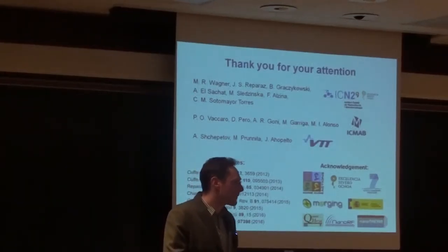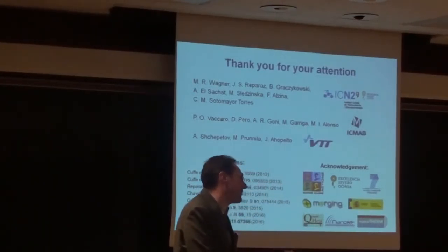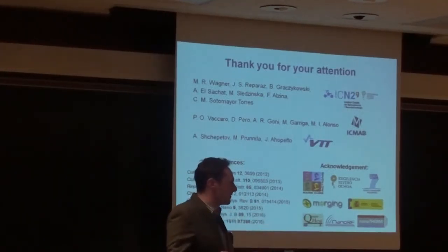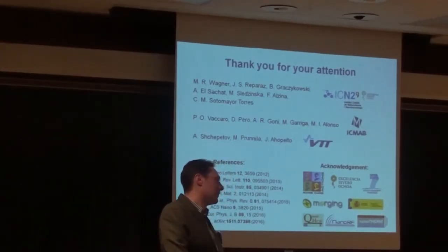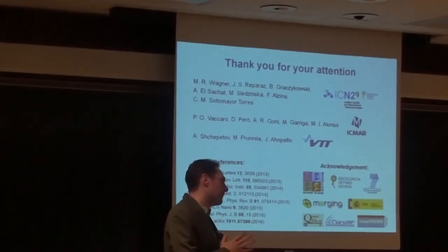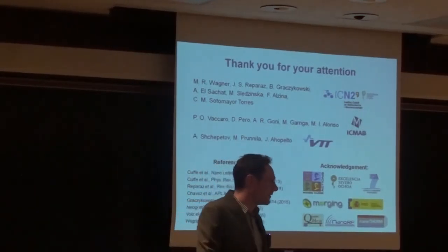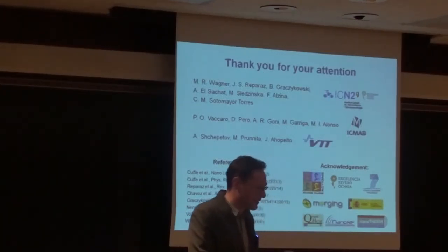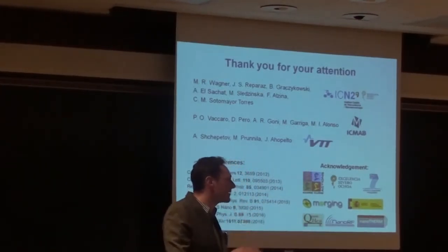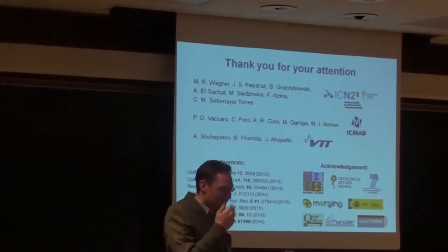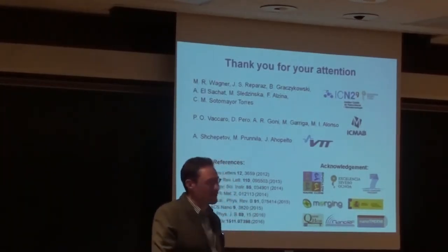Why are you doing an experiment? No, I mean, the idea is that you can basically use this for any kind of freestanding structures. For silicon, this is a reference system because it's very well studied. But you can apply this to any kind of material that gives you a temperature-dependent Raman shift. And that is a nice approach because, of course, there are a lot of thermometry works. Initially, there's the works from Balandin and graphene and so on, which are highly cited. I think it's a good point to consider this. But I think there's one main advantage, and this is...